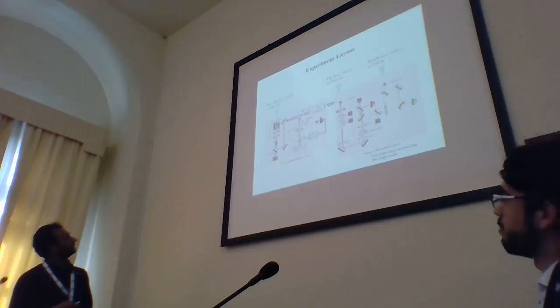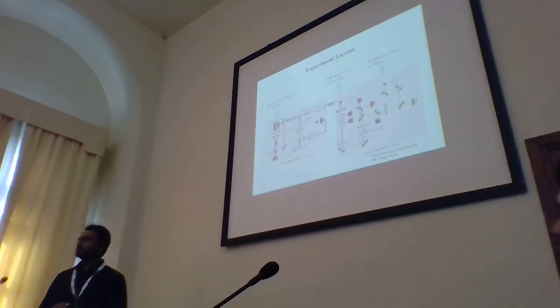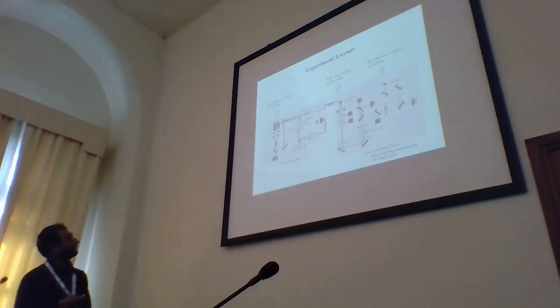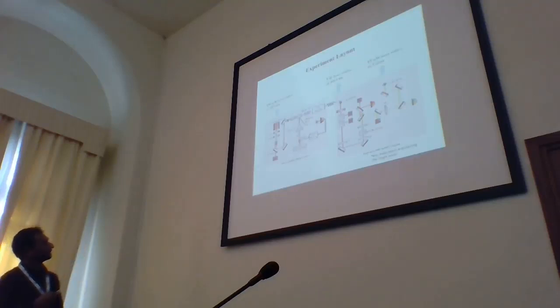So this is the experiment which I carried out. Of course, this will be done in the Virgo environment, where we have to take a pick off from the Virgo main laser. In the laboratory environment, I took a 100 milliwatt laser. We took a part of the beam to be coupled to a fiber collimator. This is all free space optical beam. It couples to an optical fiber. Then we have an intensity stabilization loop using an acousto-optic modulator. That stable seed beam is given to a 5-watt fiber amplifier. At this port, taking 1 milliwatt of infrared laser light at 1064 nanometer as an input, we can generate up to 5 watts of infrared laser light at 1064 nanometer.